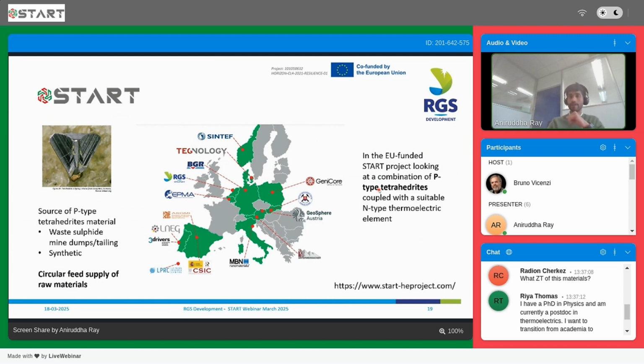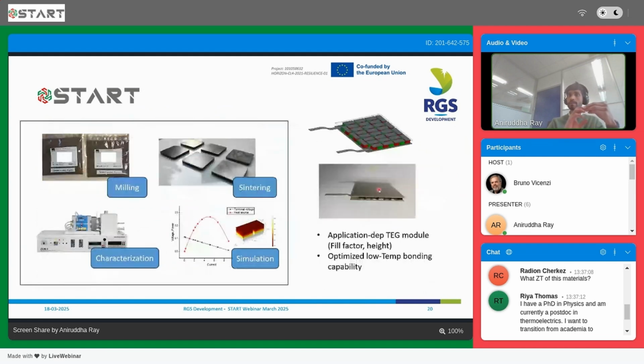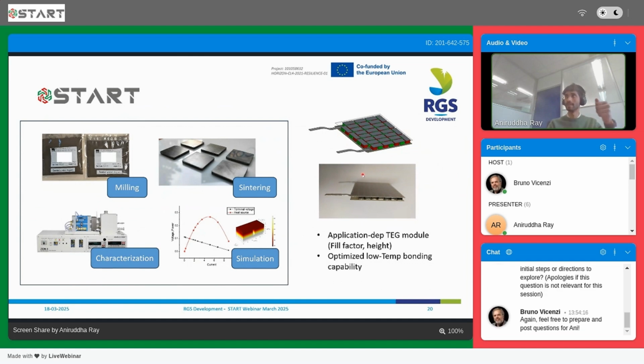And we have also already started doing all the processing steps for such a module. So milling in large batches, sintering the discs, and then characterizing them so that we can simulate the optimum unicouple dimensions so that we can get the right temperature deltas across the module. So we have started producing our first modules. You can see it on the right side over here. We simulated it, and then we made all the tooling so we can get an application-dependent TEG module. So with the optimum fill factors as well as heights.